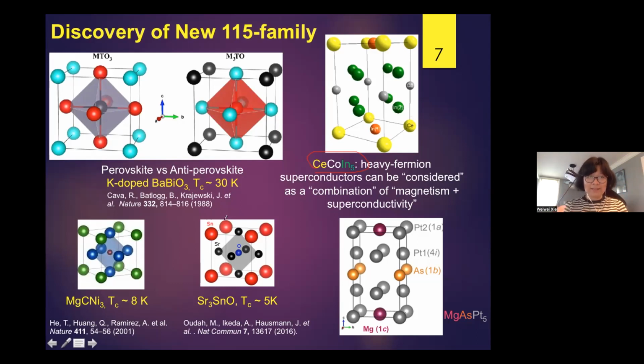The idea also comes from perovskite and anti-perovskite compounds. A lot of perovskite compounds host superconductivity. For example, potassium-doped barium bismuth oxide, where the TC can go to 30 Kelvin. This is almost the highest among oxides other than cuprates. And then there is MgCNi3, which we call an anti-perovskite structure, because the transition metal goes to the oxygen site and the main group element like carbon goes inside. And for example, Sr3SnO, this is also a superconductor.